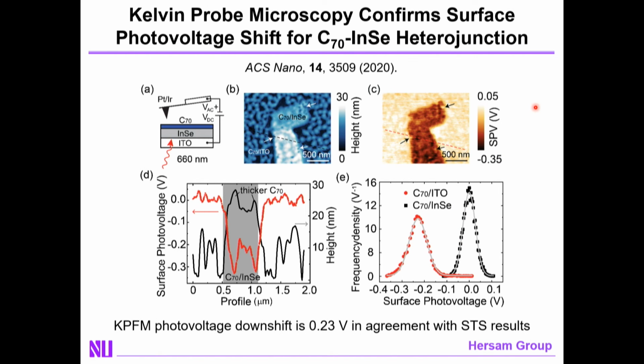To confirm that this is indeed a real effect, we performed additional characterization, in this case Kelvin probe microscopy. Kelvin probe microscopy also very clearly shows shifting in the energy level. The measured value here is 230 millivolts, in close agreement to the 250 millivolts we observed with scanning tunneling spectroscopy. So this does appear to be a real effect. Why does it occur?